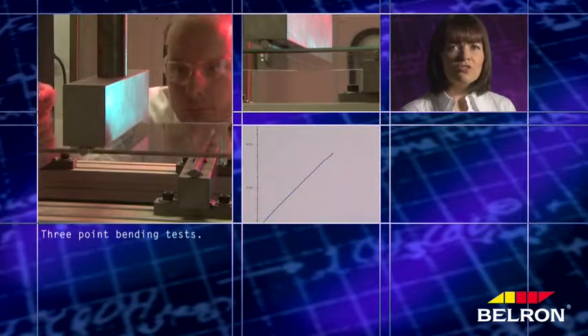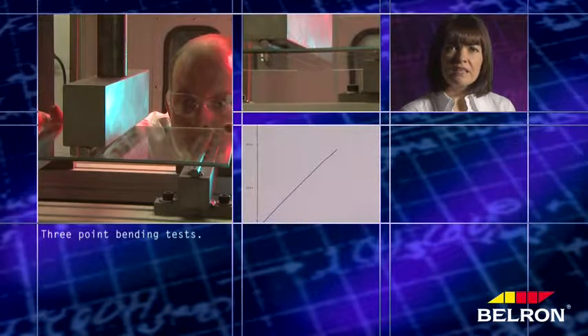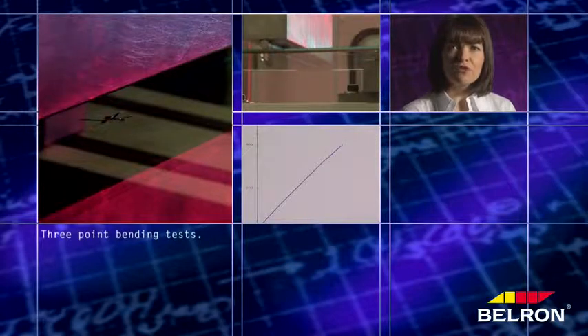They took a lot of laminated glass samples and made Starbreak chips in half of them. Then they put them in a calibrated 3-point bending machine to see what would happen. They discovered that glass with a chip in it is much weaker than undamaged glass. It has a reduced instant failure strength. In fact, the reduction can be as much as 70%.